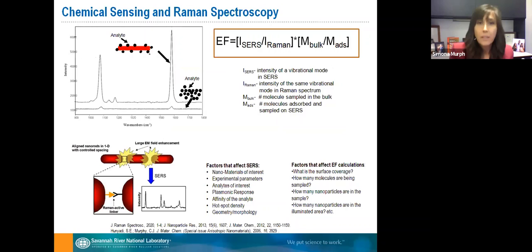So the way we are looking here at the Raman spectroscopy, you're looking at the inelastic-like scattering of the analyte. You can see here just a schematic. So you have analytes, and for each of them you look at their fingerprint response, but when you put it in close proximity of the nanoparticle, you get an enhanced response. There are many factors that influence the enhancement factor of this response. Even if you have nanoparticles that are closely together, you can actually couple their plasmon band. And also the materials, how much is in the illuminated area, and where the plasmon band is versus the laser line.